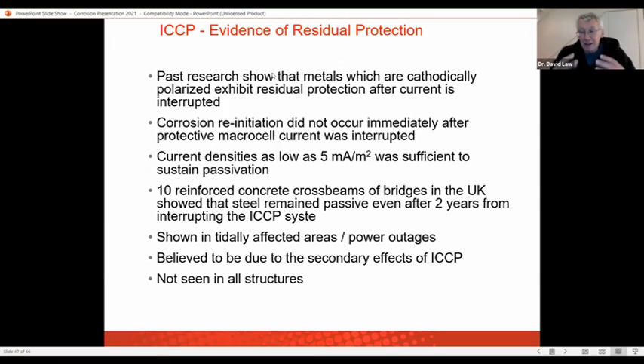So once we've done that, I said you've put on that protection, but as we're running towards the end of their lifetime, are we getting any residual protection? And anecdotally, there were suggestions that we are. And this has come where we've had fires in the TR units, and so they've been deactivated for a period of time. Sometimes they have to be switched off. Sometimes people actually even forget to switch them back on again. And so you can have periods when they haven't had the ICCP on the system. But when we've gone back and looked at them, people have seen that they are still fulfilling the criteria that they are protected.